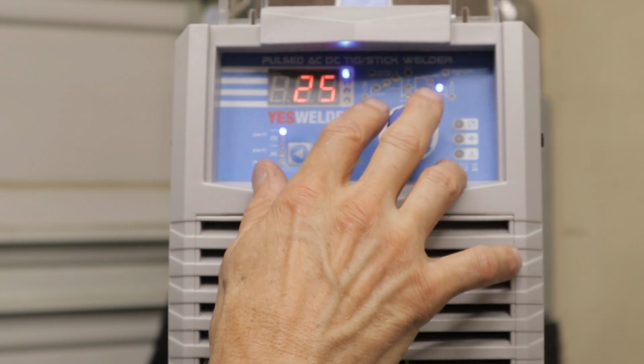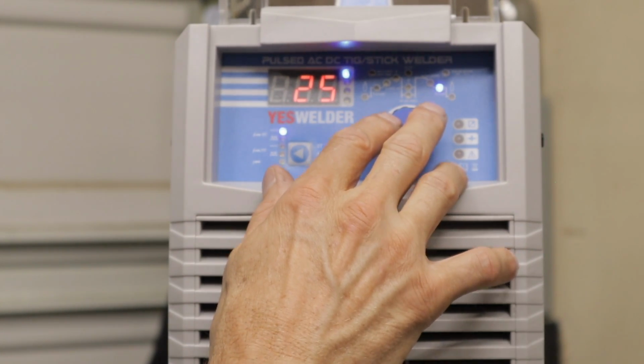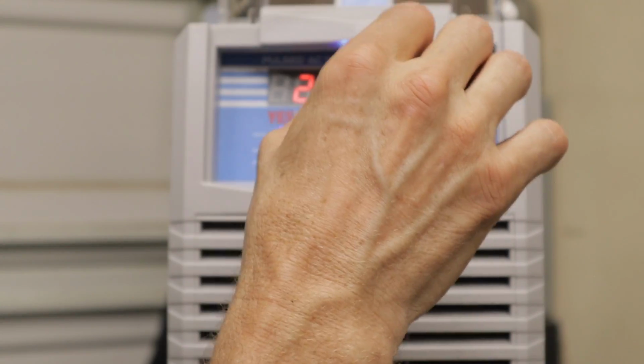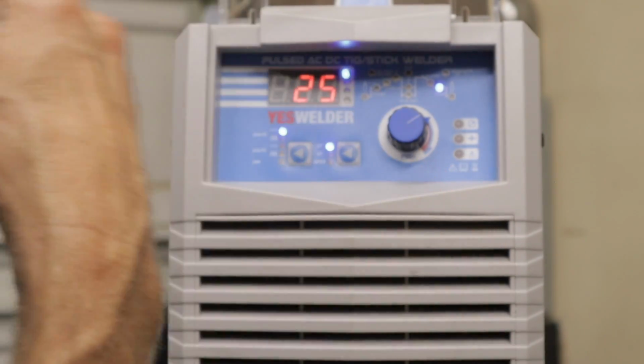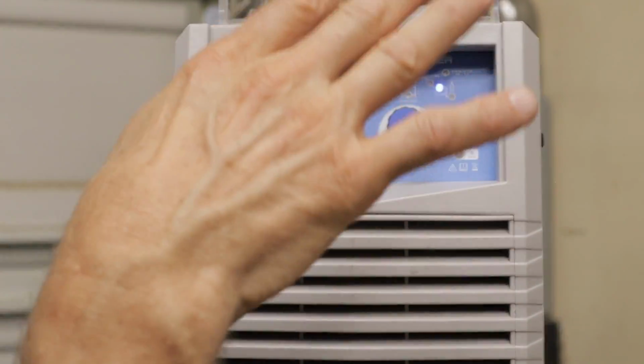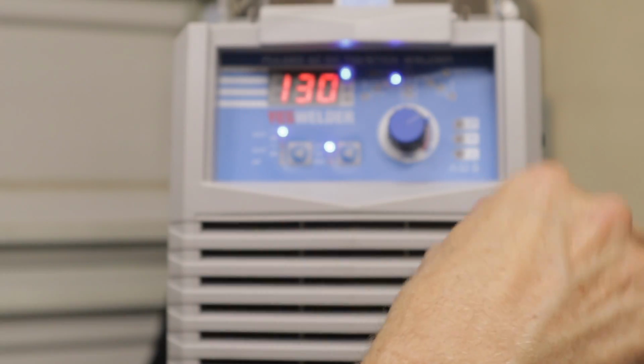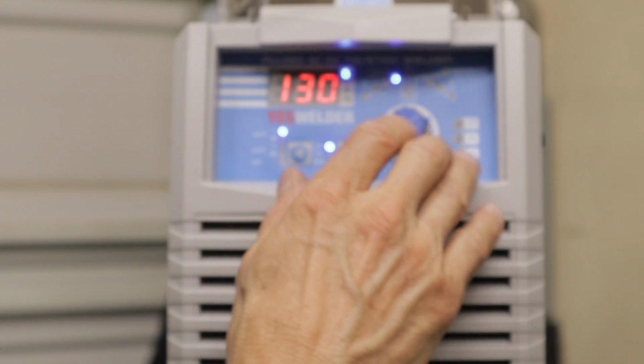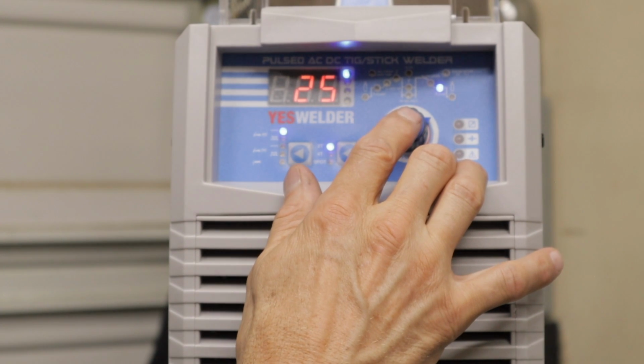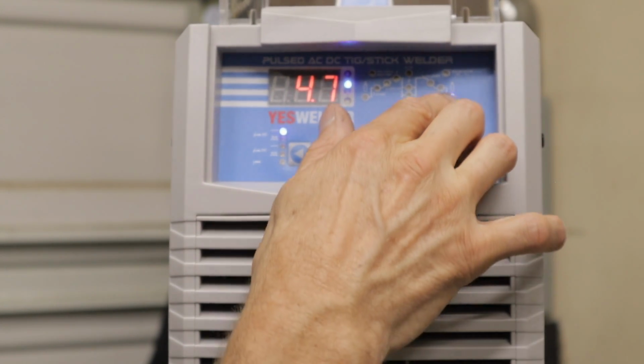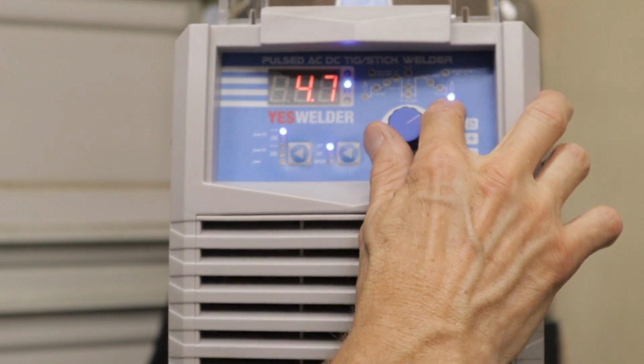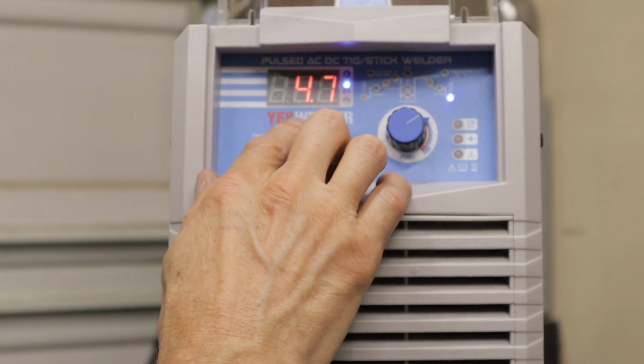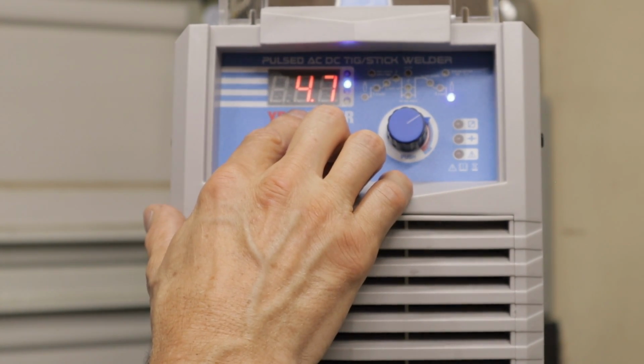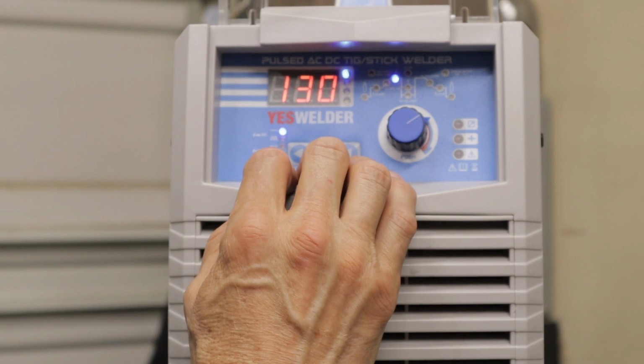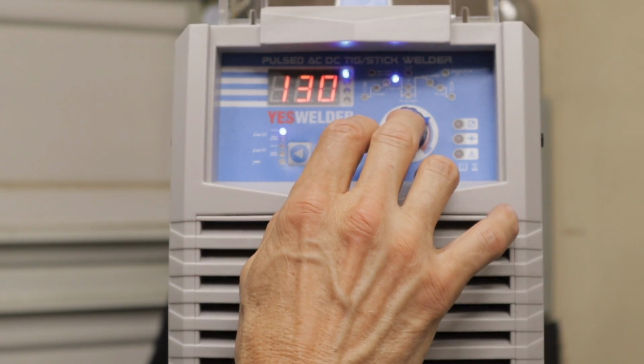The next one after that is your ending amps. It'll go down to 25 amps is what I have it set, instead of however many you were welding at. When you let off the pedal, it'll downslope and then it will go to 25 amps. And this, with your little bottle right there, is your post flow of your argon after you stop welding. I have it set for about 4.7 seconds right now.